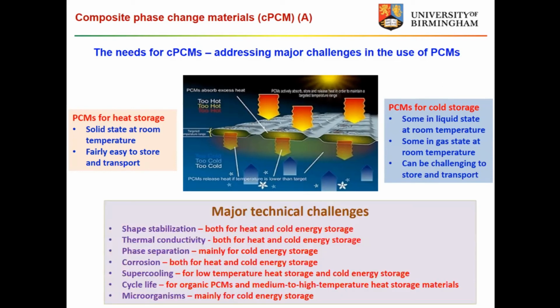And also some other technical challenges. There is shape stabilization, for both heat and cold energy storage, because how do we maintain the shape? Thermal conductivity is an issue for some materials. Phase separation is a major issue for many cold energy storage materials we come across. Corrosion issues, both for heat and cold energy storage. Supercooling is a big issue in many cases, because, for example, in our air conditioning system the feed temperature is probably about 7, and the return is maybe about 11 or 12 degrees. So you have a very narrow temperature range for being integrated with the current air conditioning system. At data centers it is the same issue.